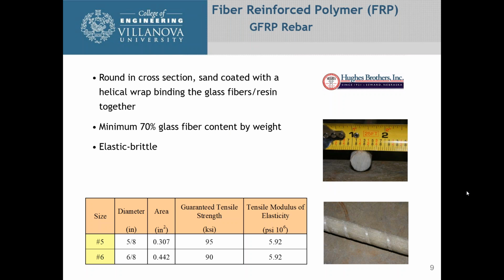And when I say elastic, you can bend them a little bit, but there is no yielding. It's a brittle failure. And you can see in the table below for the two bars that we used, we had a number 5 bar and a number 6 bar. The guaranteed tensile stress is 95 KSI for a number 5 bar and 90 KSI for a number 6 bar. But what you can also see is the modulus of elasticity is very low.